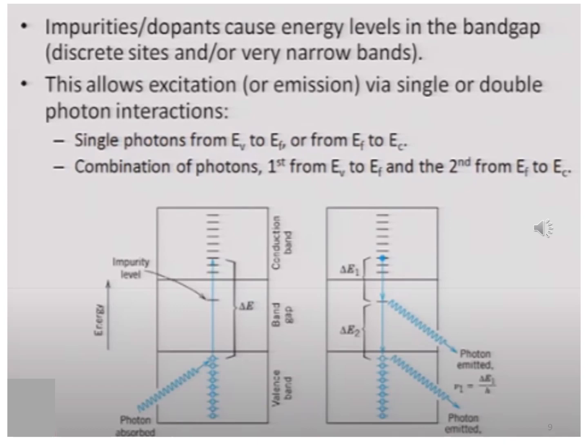We can take the example of zinc oxide as a host material or original material, and in that you will take 99% zinc oxide and 1% europium or terbium or some other species which has an energy level somewhere in between the conduction band and the valence band of the host compound.